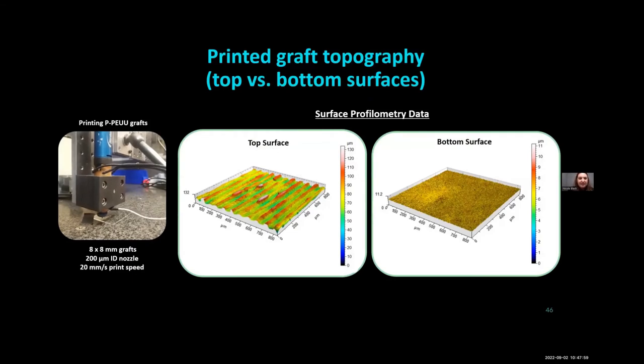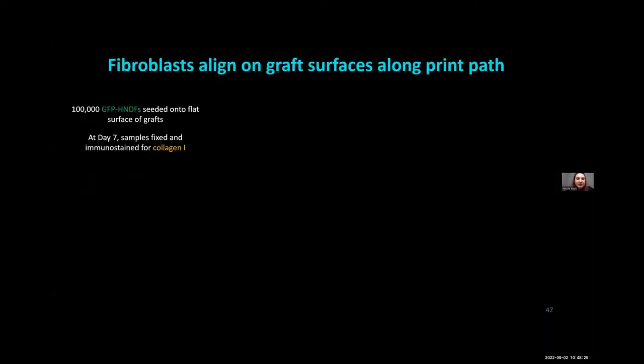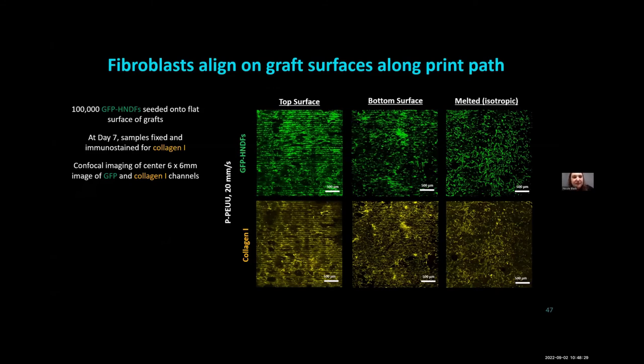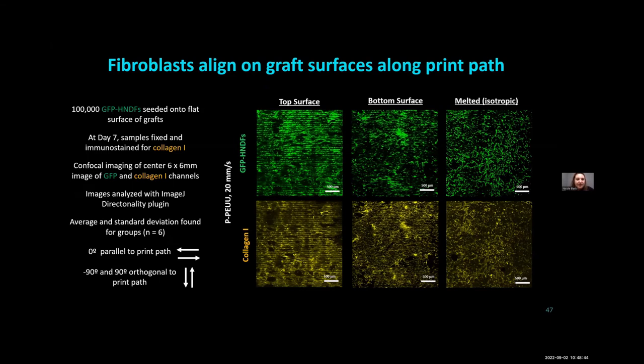And so for some of our in vitro tests, we wanted to look at how cells align and remodel these different grafts. So we were able to print these essentially little squares of the different materials, whereby the top surface has essentially mountains, peaks, valleys, topography, and then the bottom is topographically flat. And using this, we can look at cell alignment to see if we are inducing cell alignment on one or both of these surfaces. So we would essentially take these grafts, seed a GFP expressing fibroblast line onto them, fix these scaffolds, and stain for collagen 1 to see how that's being deposited. And you can run them through a software program called ImageJ to look at the directionality of the cell alignment and collagen alignment, either along the print path, which would give a peak at 0, or orthogonal to the print path, which would be at negative and positive 90 degrees.